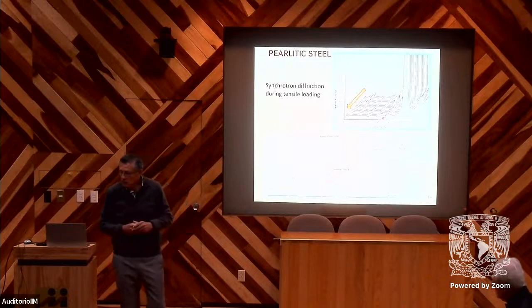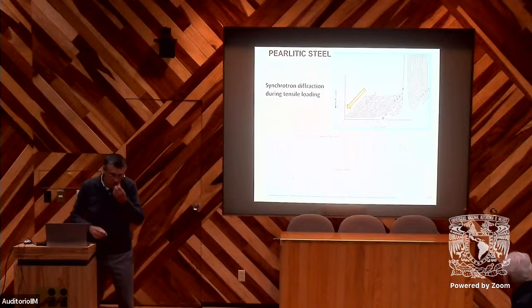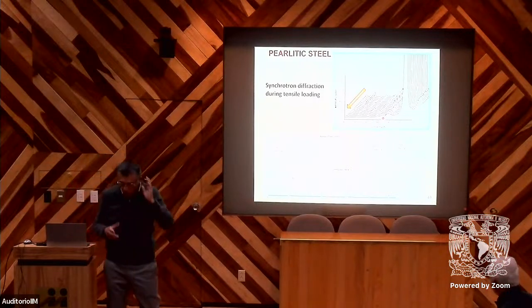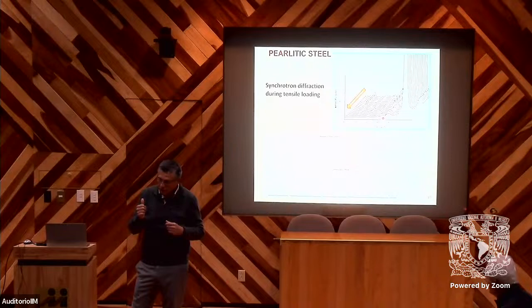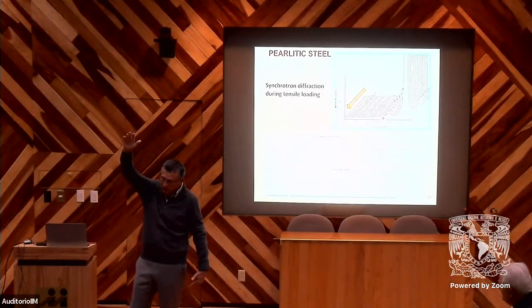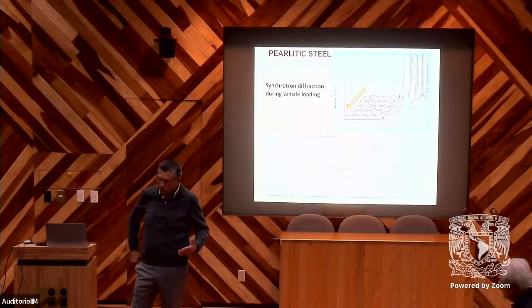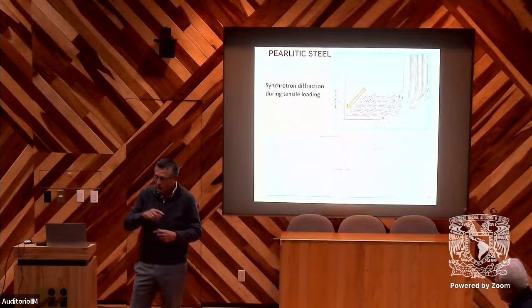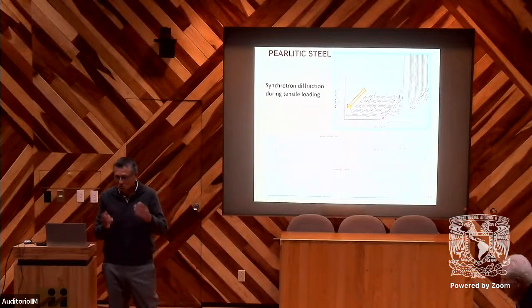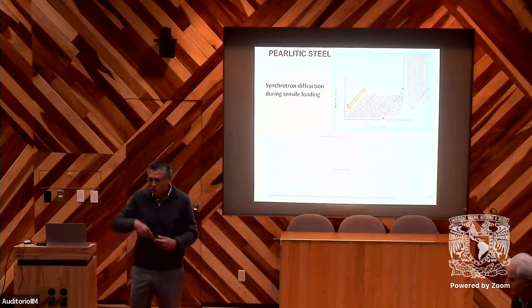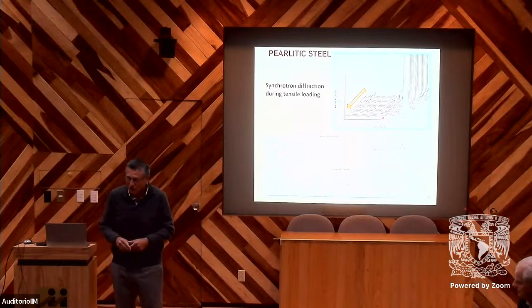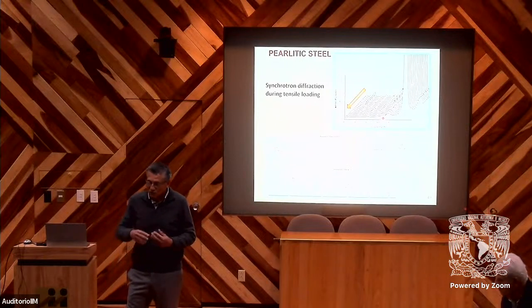Okay. And in the synchrotron, we used 30 seconds for each peak. In general, we have a very high peak of ferrite, and this is not usual. Usually people use a few seconds for one peak, 1 second, 2 seconds for a peak. 30 seconds was very long.